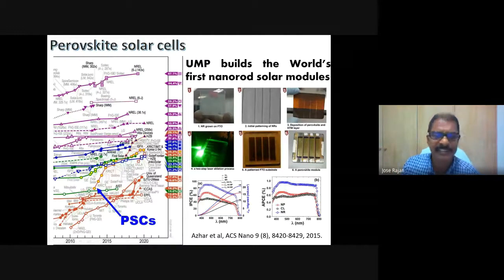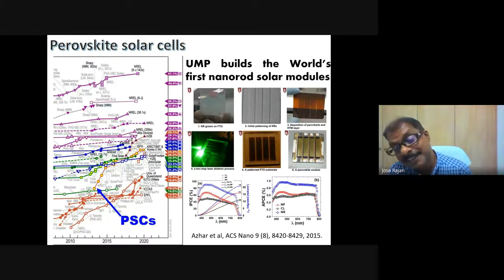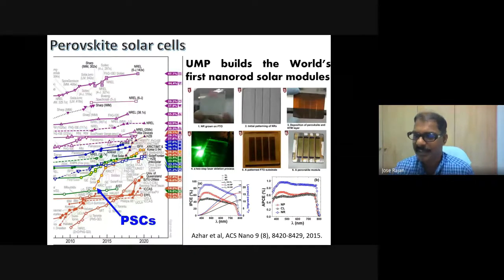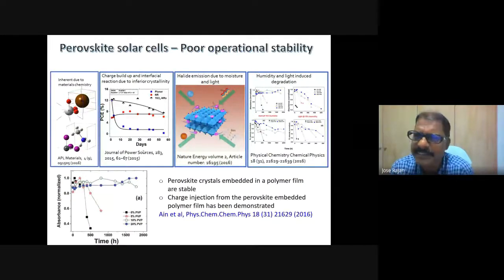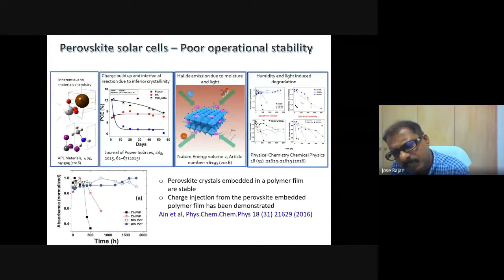From there, we not only developed this one, we also addressed a few issues of stability, which is given in this slide. The stability of perovskite solar cells is the biggest issue in perovskite solar cells. There are many theories and experimental evidences about what makes the perovskite solar cell unstable. One of them is its intrinsic instability, because even if it is not inorganic perovskite, it is an organic-inorganic hybrid perovskite. The organic part, in most cases, is a methyl ammonium halide. When you look into the symmetry and the geometry of that molecule, you will see that it's a polar molecule.